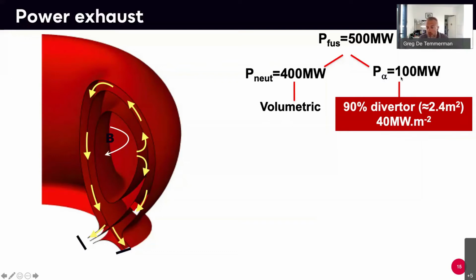So those helium particles carry 20% of the reaction, which is about 100 megawatts in this case, and they stay in the plasma because they are charged, so they are confined by the plasma. We actually use them to heat the plasma. So the plasma is basically self-heated. But basically that means I have about 100 megawatts of power inside the plasma, plus the 50 megawatts that I actually put in.